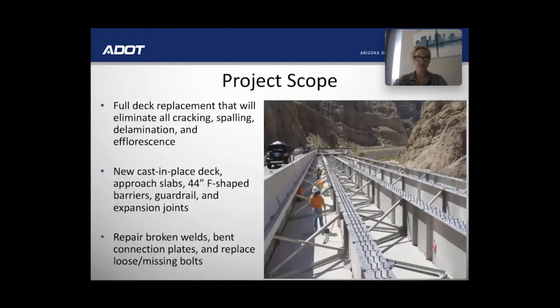A deck replacement was recommended for Virgin River number 4 due to the severity of damage to the concrete deck and based on previous experience in research analyzing the differences between a deck replacement and microsilica overlay. Since the bridge was previously rehabilitated in 2002 with an MMC overlay, it was not recommended since it did not perform as well as expected. And also a deck replacement would provide a longer service life in the range of 25 to 50 years.